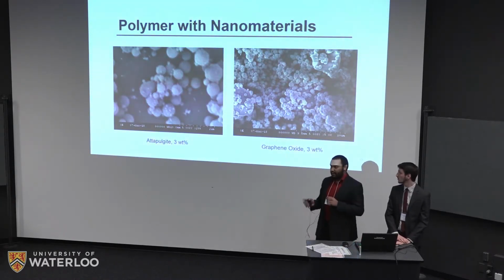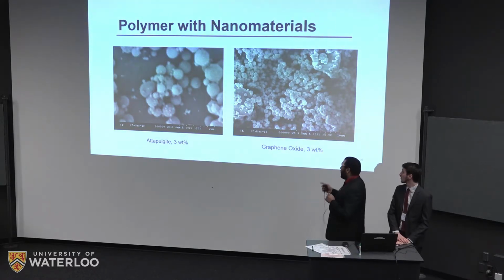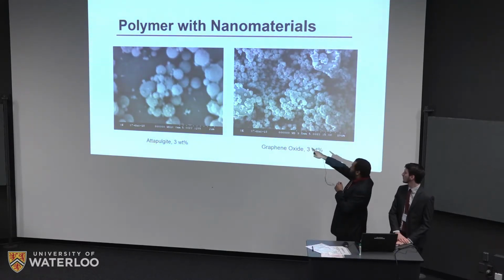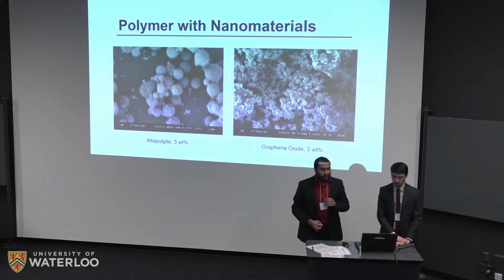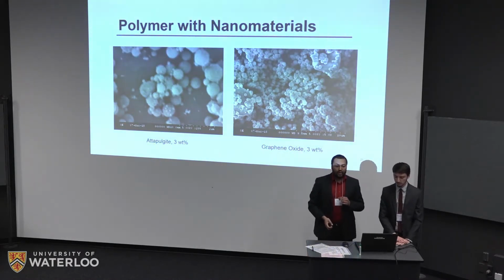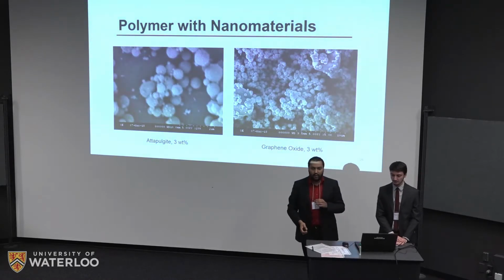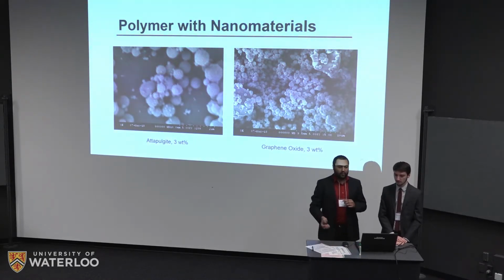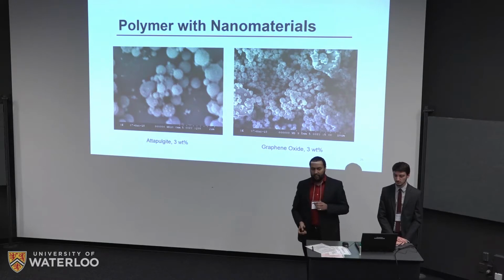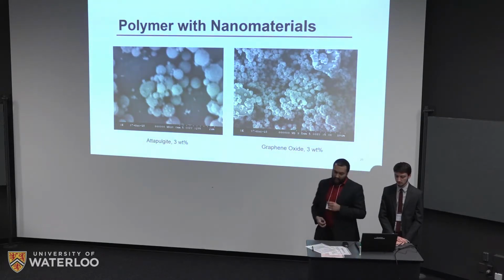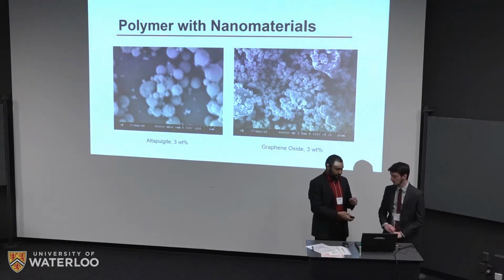I'd like to point out the graphene oxide just because it's the most evident one. You can see there are platelets around that are interspersed along with the microspheres. This showed us that we actually got really good dispersion with the graphene oxide, partly because we weren't able to test this directly with the turbidimeter. But yeah, that's what we were looking for.